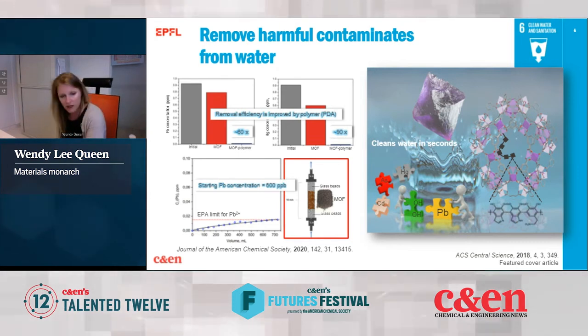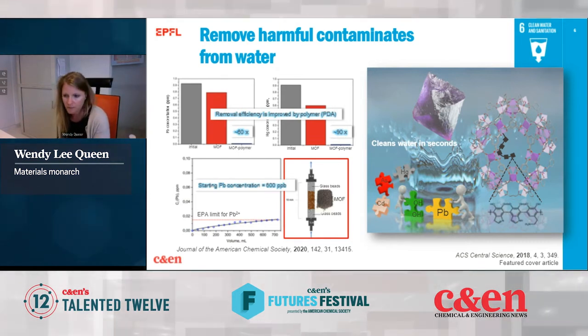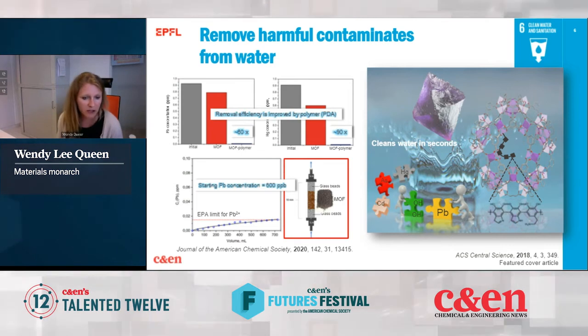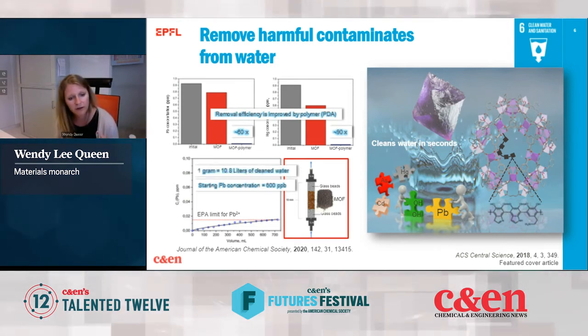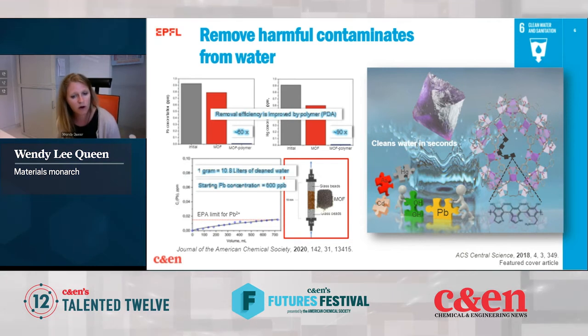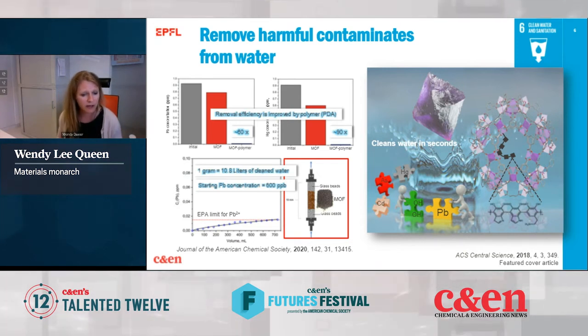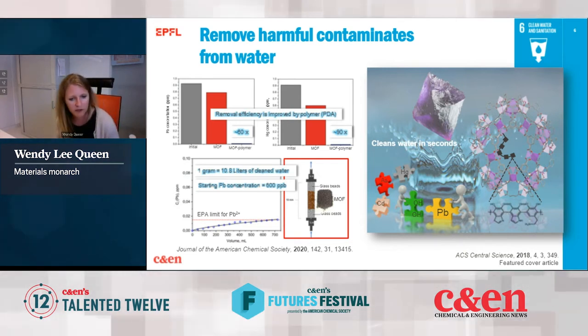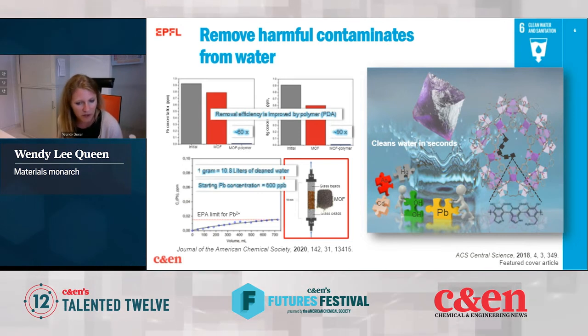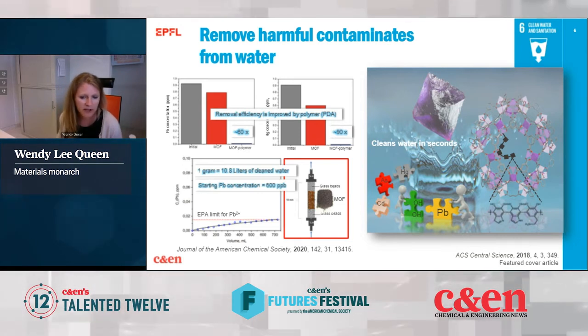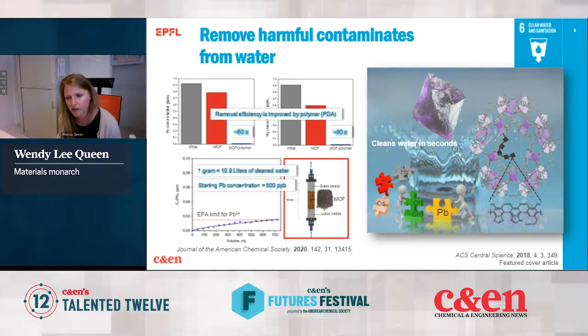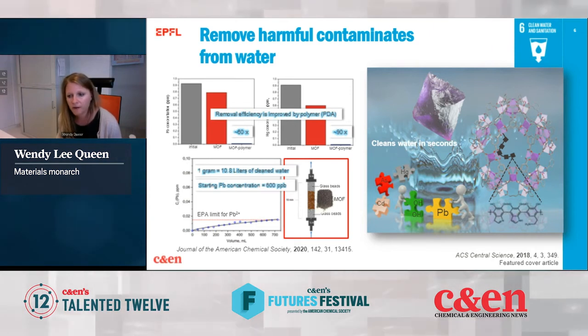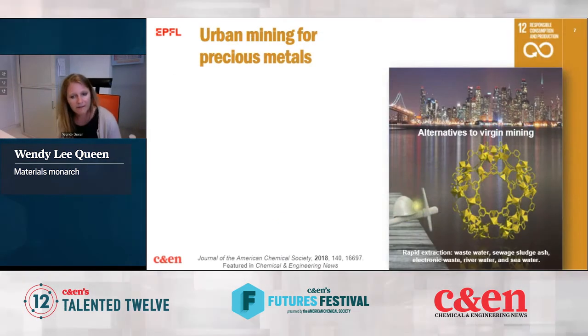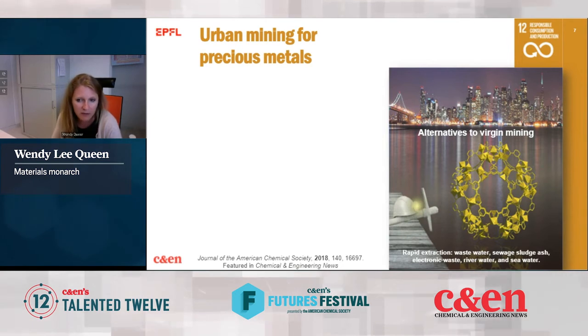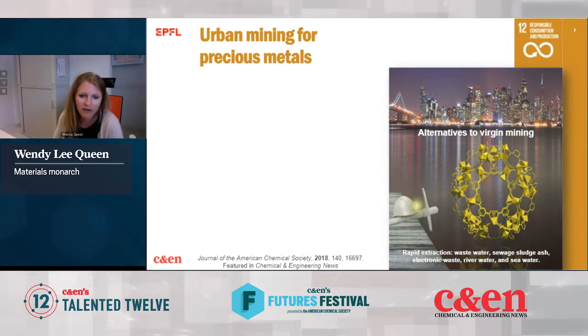And what we find in this flow-through experiment is that we can actually purify with a single gram of material about 10.8 liters of water. And this is great because it's already competitive with commercial adsorbents. Furthermore, we know that we can improve this quite a lot with improved polymerization as well as better structuring processes to form our beads.